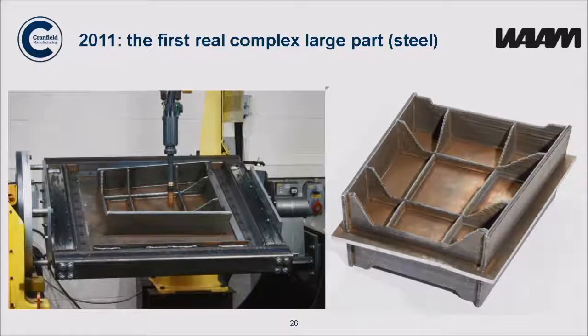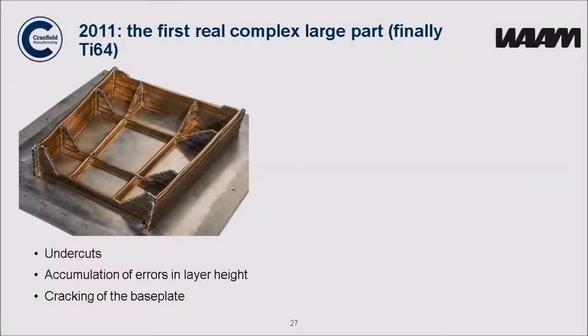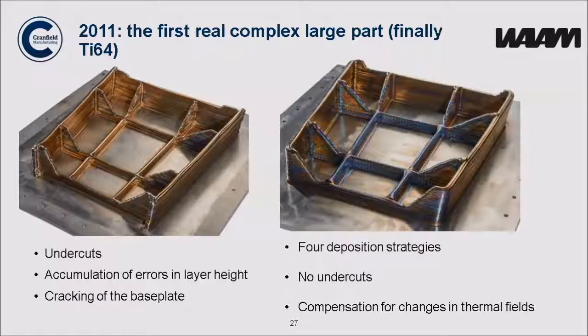So this is the landing gear rig. This was the first variant that we made in steel. So we made this actually, and it seemed pretty good. So we went on to make the titanium version, and actually it was horrible. It had lots of undercuts, it had accumulated errors in layer height, we had cracking of the base plate, all sorts of issues. But you have to find out how to solve these problems, and this is the final part.